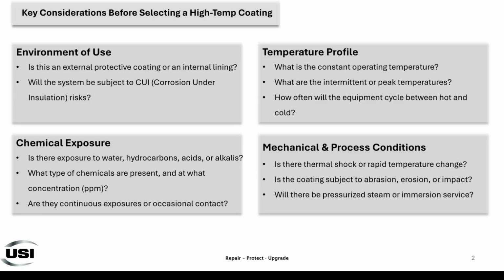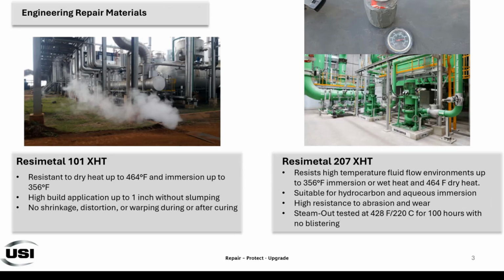And I'm going to share with you a few, and then we'll open it up to questions because we like to keep this interactive. There's two newer systems that Resimetal has come out with. One is a 101 XHT, which is actually a repair compound that can handle up to 464 degrees dry heat and immersion temperature up to 356 F. And you can build it up to an inch thick without slump. There's no shrinkage or distortion once it cures. It is a Novolac system, so you do want to make sure you mix it up thoroughly, but it's pretty easy to mix up and apply.